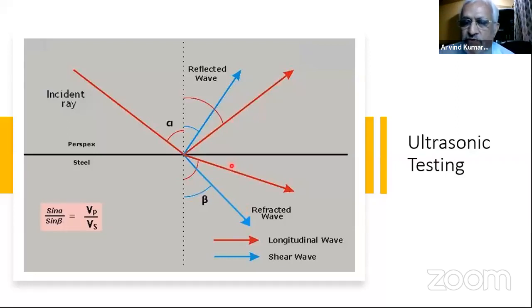So with these two waves of different velocities, they will be going in and coming back, and you're not able to interpret what's happening, like which wave has come back and what is my defect indication, what is my actual wave which has come back. Now what we do is increase this angle further and try to remove this wave from the material. As I increase this angle, at one point I will have this wave parallel to the surface, so no more is introduced in the material. That is the time I have only shear wave in the material.